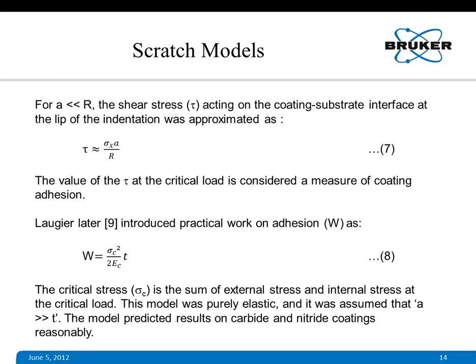When this contact radius is very small compared to the radius of the tip, shear stress can be expressed as equation 7, tau is more or less equal to sigma x into A by R. So if we can find the tangential force at the critical point, we can obtain or calculate the shear stress, which in turn will give you the adhesion strength of the coating.